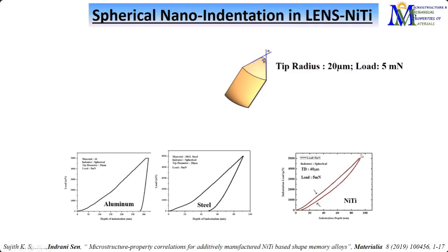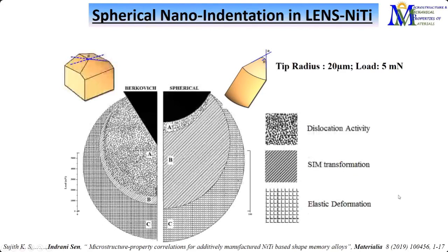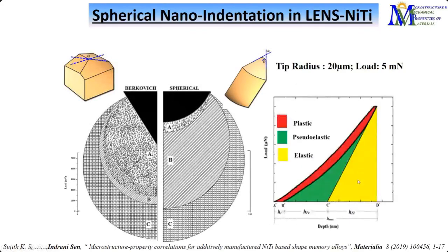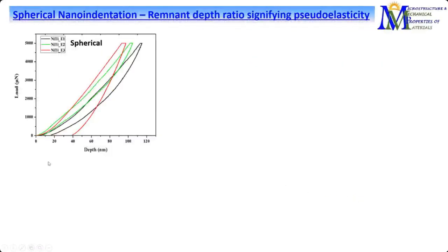And in nickel titanium, we can see that a major part of the load that we are applying is being recovered. This significant part is being recovered completely because of some internal activity of the phase transformation that is happening. This entire green and yellow part is being recovered, and that leads to the recoverability or the pseudoelasticity of the system. Now, what we have seen to our surprise is that the one prepared with a moderate amount of energy, the green one, shows the most recoverability, whereas the red one, prepared with the highest energy density, although it shows higher strength, also shows a very high amount of plasticity, which means that its recoverability or shape memory capability is much lesser.